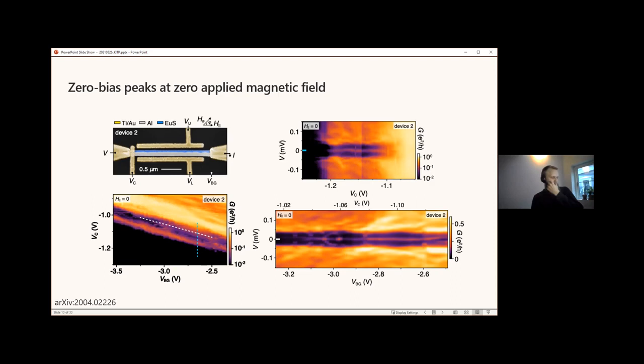I would assume so somehow, because, well, I think you don't have to suppress the parent gap. Essentially, what you're interested in is suppressing the induced superconducting gap. And if it's the induced gap of the single channel, in the best case, then preferably you only couple the europium sulfide to that channel and not to the superconductor. In our case, experimentally, it's easier said than done. But yeah, I'm not sure if that answers the question.